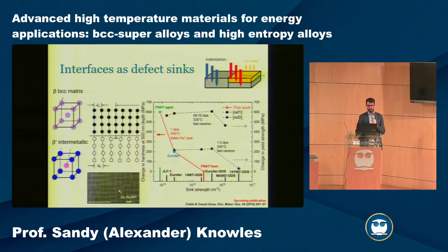This is work from Steve Zinkle and others in the US that have done a lot of work on these so-called oxide dispersion strengthened materials. These are powder metallurgy-based routes where you can create very fine-scale microstructures, but it's a technique that's quite hard to do repeatably, very hard to scale up, and also very expensive. For us, we're using a relatively cost-effective, typical casting method, the same as you would see in a normal casting foundry, but just at a lab scale.